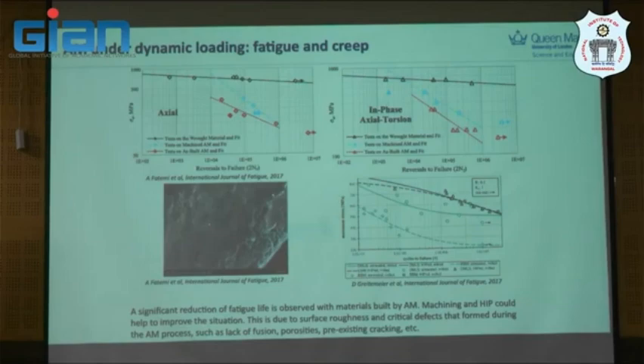Last but not least for my section, not finished yet, but this is just static, fatigue, creep. You will see that whether you have AM, or machined from AM, or rod, the different material manufacturing process contributes to different cyclic, or what we call time-dependent, property here. This is the fatigue, the number of cycles to failure. You will see that for the non-AM one, this is one thing, but if you have AM and you machine the sample from the AM build, they get a different property from the as-printed sample as well. You follow me? If you print it and then pull it, it's different from if you print it, cut it, and pull it, because of the surface effect.